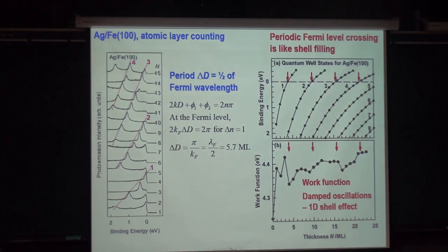And then the important thing is, for example, with 5 layers the peak is here, 6 layers here. At 5, we see no peak at 6 and no peak at 4. So 5 is 5, there's no 6 and no 4, so everything is exact. So we plot the energy positions of these quantum well states, for A 1, 2, 3, 4, 5, 6, as a function of thickness.